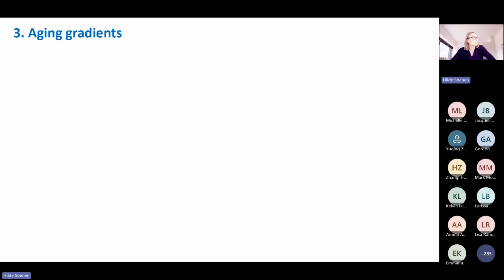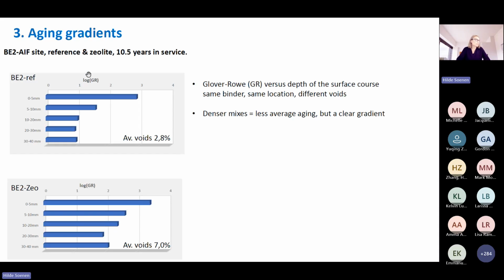Regarding the aging gradients, how the aging penetrates through the pavement or to the surface layer, I have here some slides from the Belgian side where we had a reference and a zeolite. And you see the Glover-Rowe versus pavement depth. In this case, the air voids are 2.8, and this one has a bit more air voids. But you can see, even for the very dense asphalt, you still have quite a gradient. And on average, it is aged less compared to one with higher air voids, but the gradient is even larger.